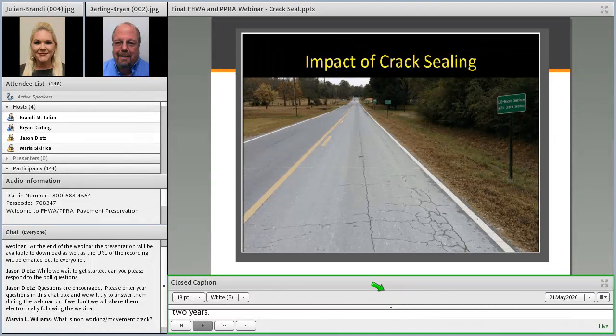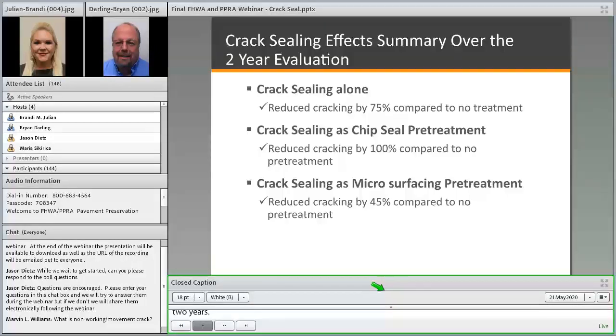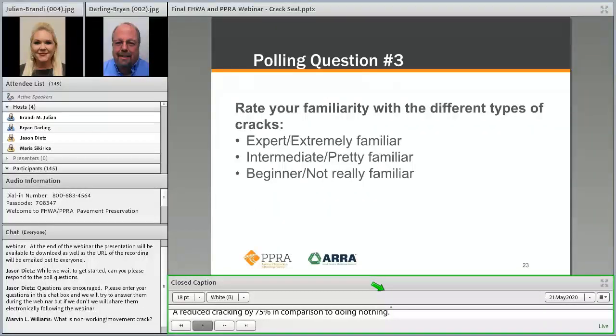So again, this shows that the performance enhancement from crack sealing as a pre-treatment really helps extend the performance of all of your other surface treatments. The impact of crack sealing was published by NCAT. They said that as a standalone treatment, crack sealing reduced cracking by 75% in comparison to doing nothing. It reduced cracking 100% with a chip seal in comparison to not crack sealing first. And with micros, it reduced cracking by 45% for microsurfacing treatments. So really good data coming out of there.